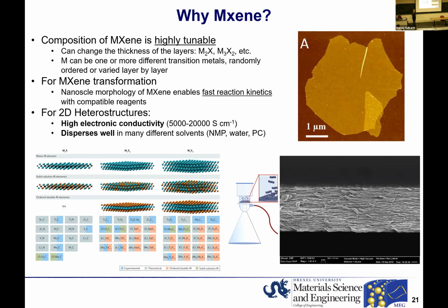And some of you might know that in my department, I have great colleagues, Professor Yuri Gogotsi and Professor Michel Barsoum, who in 2011 discovered a new family of two-dimensional materials called MXenes. And these are essentially layered transition metal carbides, nitrides, and carbonitrides. But what's important for us is that these MXenes can be chemically very versatile, so they can serve as chemically rich precursors for the synthesis of other classes of materials. And also the morphology of these particles is two-dimensional, and it's at nanoscale, which implies that we can see increased reaction kinetics when we transform these MXenes into, in our case, oxides.